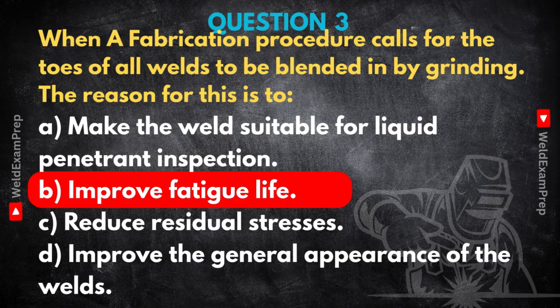By carefully grinding and blending those transitions smoothly, making them more gradual, you effectively increase the radius at those points. You smooth out the stress riser. This lets the applied stress distribute more evenly over a bigger area. And that really dramatically extends the service life of the component. It's crucial for safety and reliability wherever fatigue is a factor.